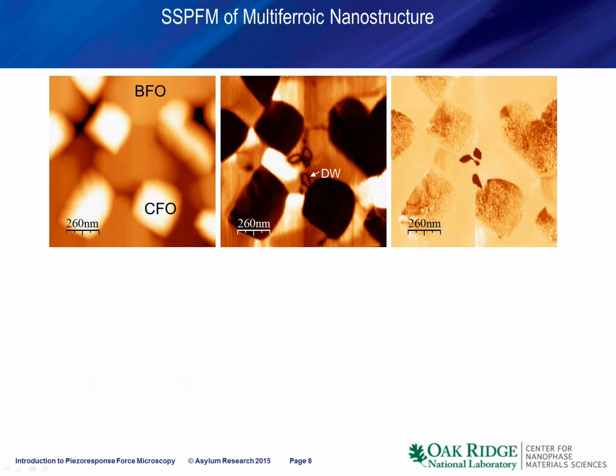So, the first example of such structure is the tubular structure formed by the cobalt ferrite in the bismuth ferrite matrix. Shown in the top row is the surface topography, so you see these nice cobalt ferrite islands, and piezoresponse phase and amplitude images. In this case, you can see that bismuth ferrite is ferroelectric, as can be expected, and cobalt ferrite is not ferroelectric, as can also be expected.